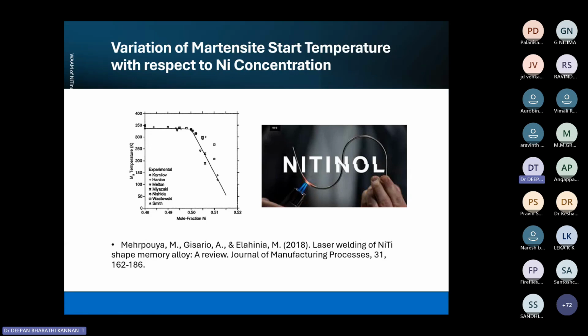So this is one of the major challenges that we may face whenever we are doing welding and also wire cutting manufacturing, because we are exposing the nitinol to higher temperature. Obviously this will have a negative impact on the chemical composition, and in turn an effect on the shift in the martensite start and martensite finish, as well as austenite start and austenite finish. And in some cases, as I said in the first slide, we may also notice a phase called R phase, which may shift the martensite start temperature. So that is also another challenge with respect to wire cutting manufacturing.